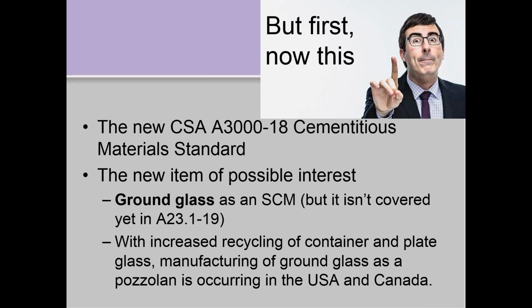And just to mention the cement standard, which came out last year, one item of possible interest is that we're looking at different supplementary cementitious materials. We have fly ashes, slag, silica fume, and some natural pozzolans, but one that's been introduced is ground glass, municipal ground glass that's been collected and crushed. It's not covered in the A23.1 2019 yet, but it probably will be in an amendment.